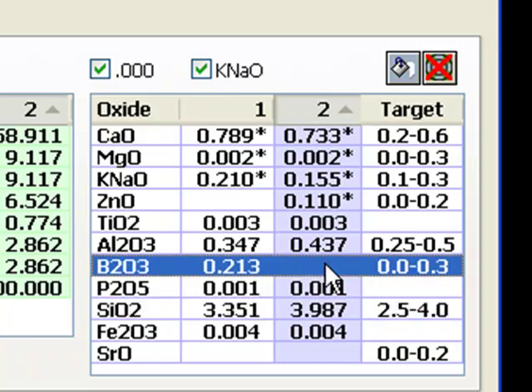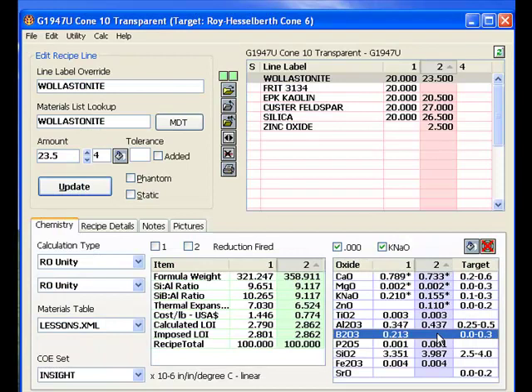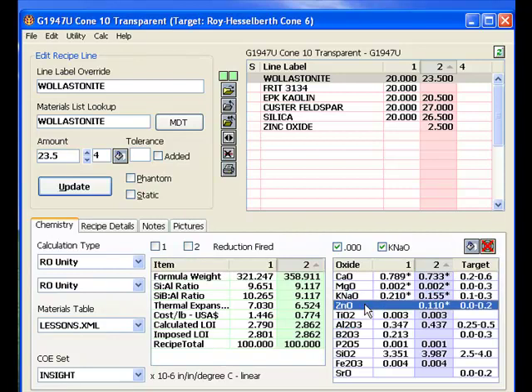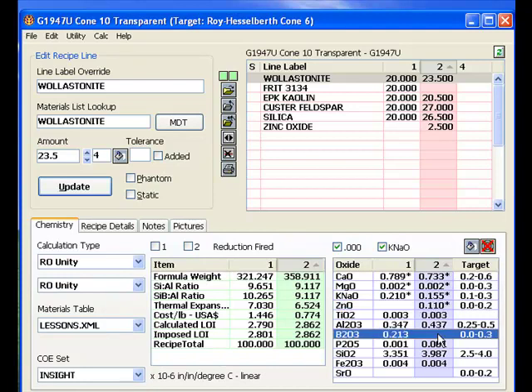The big difference is here: B2O3, or boron. Amazingly, many people use frits and materials like colemanite and gerstley borate without ever knowing about this magic oxide that these materials contribute. It is a low-expansion, low-melting glass — exactly what we need to reduce the firing temperature of a Cone 10 glaze. Without boron, we would have to try with zinc, sodium, and lithium. Sodium is high expansion. Zinc conflicts with many colors. Lithium can only be used in small amounts or it causes glaze defects. Plus, they just do not melt the way boron does.